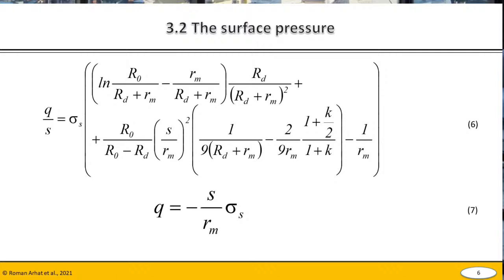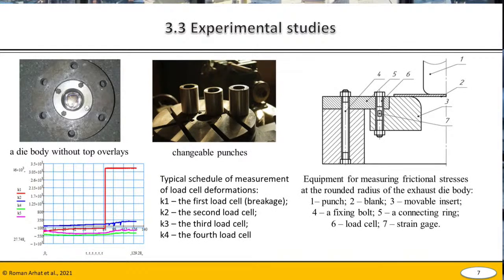To verify the obtained dependence for the determination of contact pressure, experiments have been carried out to measure the load cell deformation caused by frictional force. Slide number 7. The experimental data are used to verify the adequacy of the mathematical model of the distribution of contact pressure on the die body around its radius when drawing without collet. Next slide,